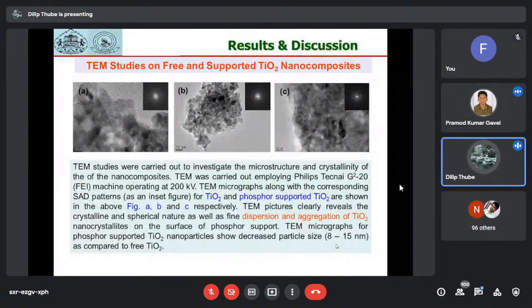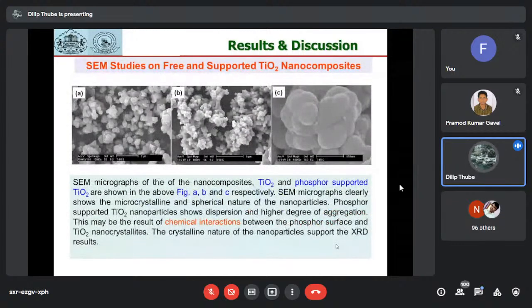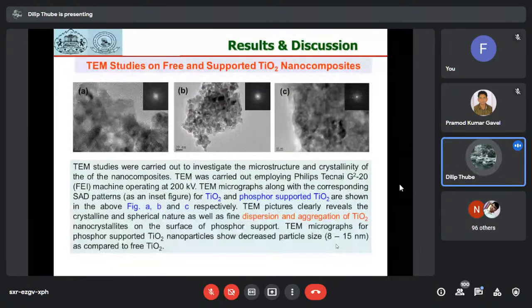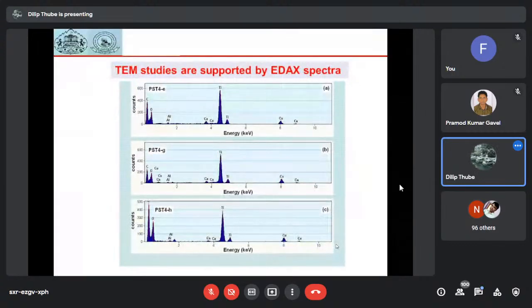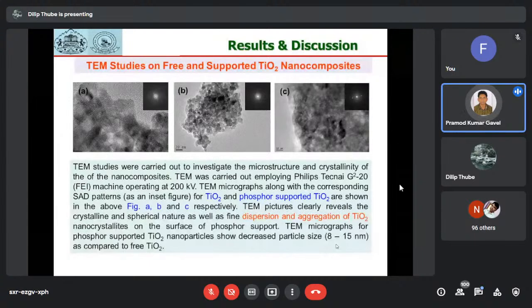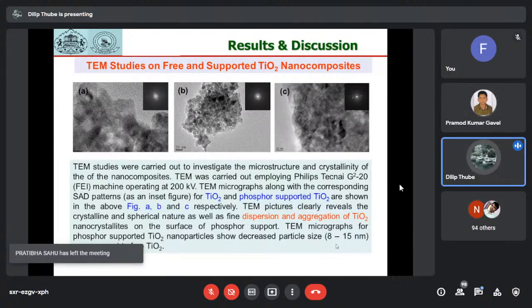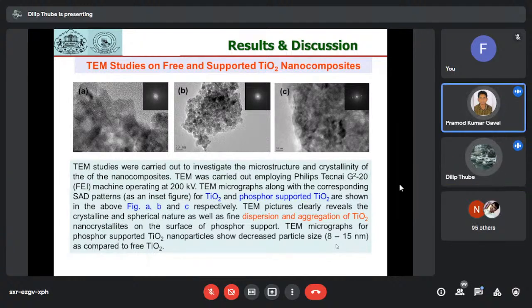There is dispersion as well as aggregation of the TiO2 material. And if you look into this picture, there is an aggregation as well as what we have stated. The TEM micrographs clearly indicate that the particle size is decreased due to the chemical interactions between the phosphor material and the TiO2 material, and is about 8 to 15 nanometer. After aggregation, the particle size is decreased or increased? Particle size is decreased, sir. So that is why I am saying, there is aggregation, but there is no growth in the particle size. So it should be decreased for better photocatalytic activity, as you said previously, quantum confinement.